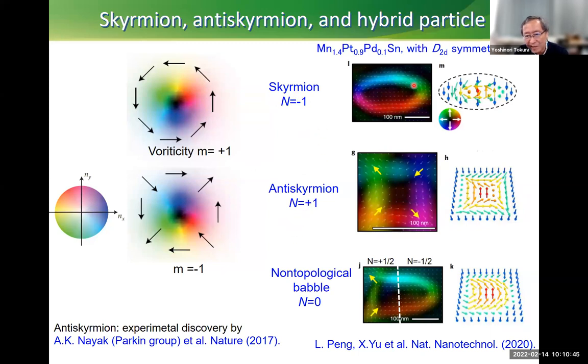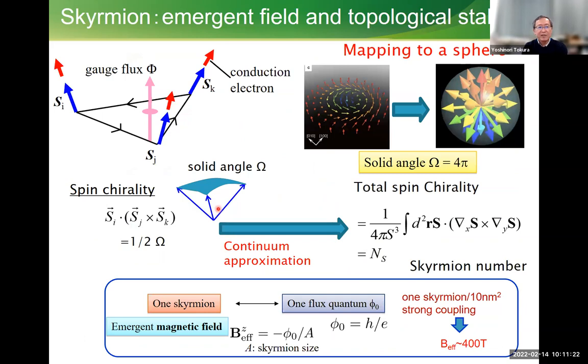For example, this is just an elongated skyrmion, but if you cut around here, the topological charge around this region is one half, and this is minus one half, and this is plus one half. Then if you combine these two states, you have plus half and minus half, defining a non-topological bubble, namely n equal to zero, topological charge zero. Such a variation from particle to antiparticle through the hybrid can be observed in real materials. So here, let me start with some emergent electromagnetic fields enabled by these topologies.